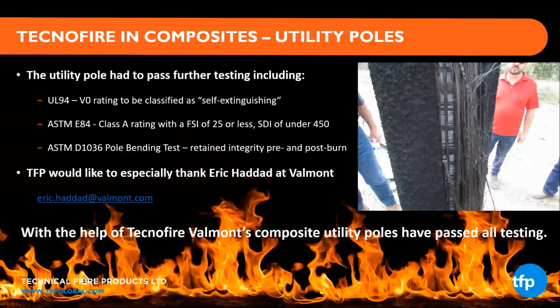As well as the extreme wildfire test, the poles also had to pass UL 94 V0, ASTM E84 Class A, and the D1036 pole bending test, so a wide range of demanding tests assessing fire retardancy, fire resistance, and retention of mechanical properties. And the insulating carboniferous char is clearly visible in the photo on the right of the slide. And I'd like to thank Eric at Valmont for working with TFP to make this project a success and for letting us present the results today.